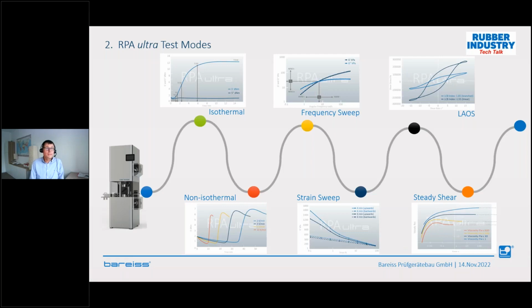So which typical test methods are available in an RPA? For example, we have an isothermal test, a non-isothermal test, a frequency sweep, a strain sweep, and LAOS, which means large amplitude oscillatory shear. It's also a strain sweep, which goes to very high strains, that's all. And then finally, we have a steady shear mode, which I will explain later.